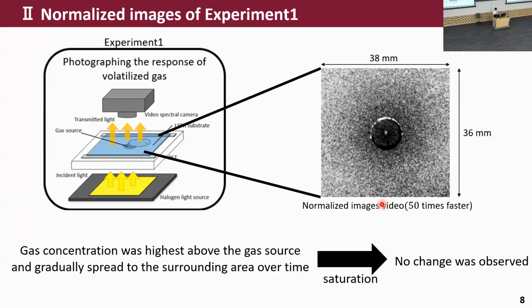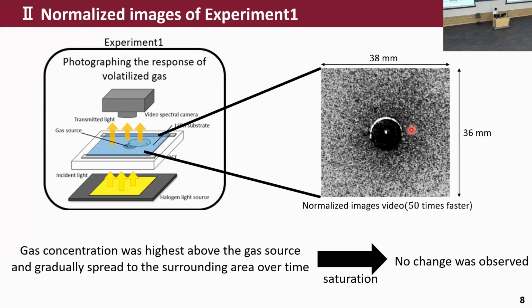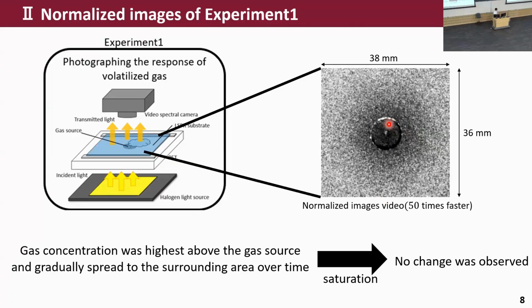The video shows the diffusion of volatilized gas at 50 times the normal speed, and it was possible to confirm that the gas concentration was thickest around the gas source and gradually spread to the surrounding area over time. As the gas saturated, there was no change in the distribution of gas concentration over time.